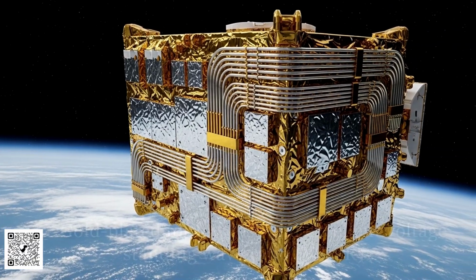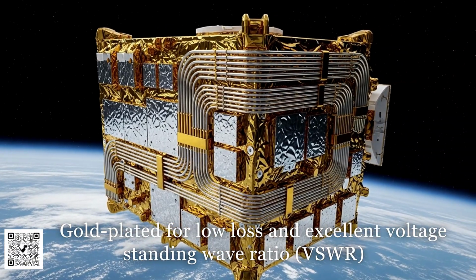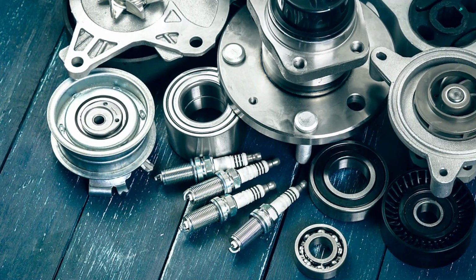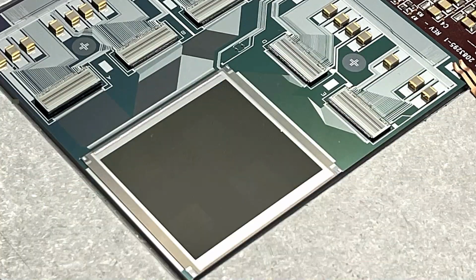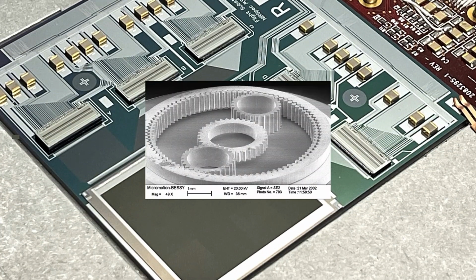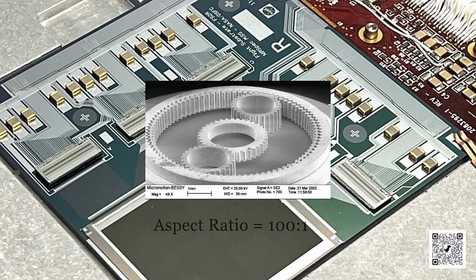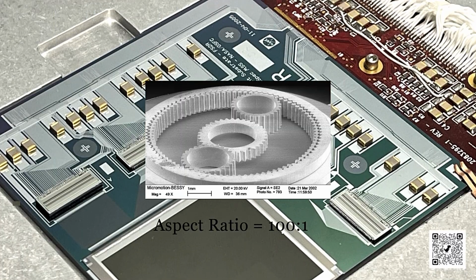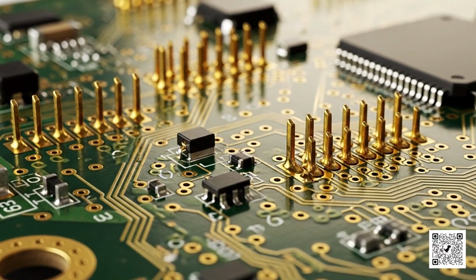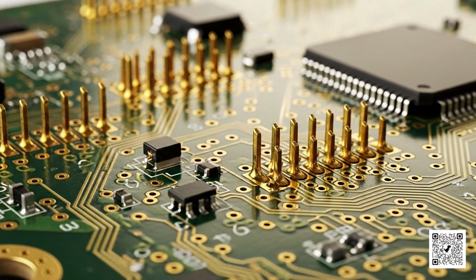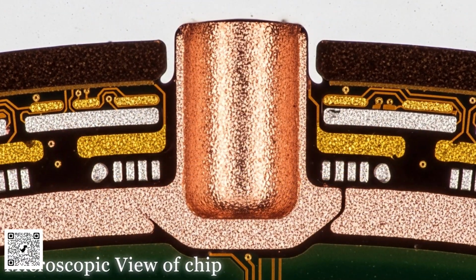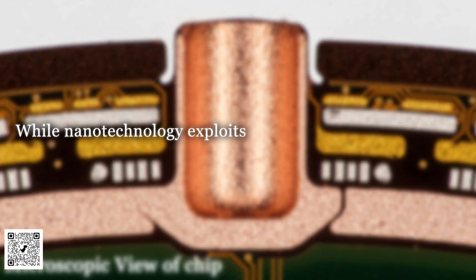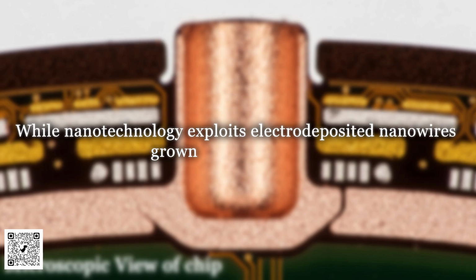Satellites still rely on gold-plated waveguides, automobiles on zinc or chrome anti-corrosion skins, and MEMS systems on LIGA-plated microgears with 100:1 aspect ratios. Modern electronics depend on gold-plated contacts and void-free superfilled copper vias, while nanotechnology exploits electro-deposited nanowires grown in templates.